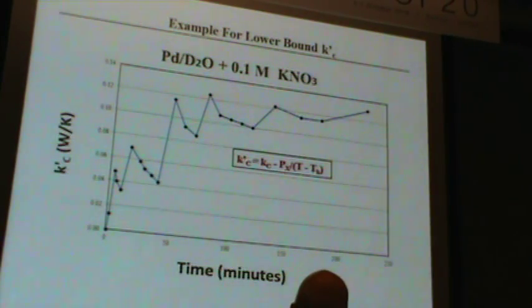This is my example of a study I did this summer using the lower bound. I'm hoping to get a negative value, but as soon as I took the first measurement, it's already 0. But it gradually goes up. There's some excess heat produced early on, so it kind of goes up jaggedly. But I get the regular trend is like this. This is getting close to the correct value. As time goes on, your difference in temperature gets larger, and you approach closer to the correct value.